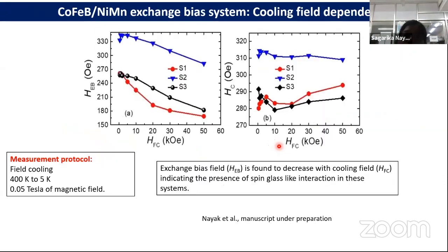Similar to our previous study, in this study also we performed a field cooling dependent study to study the role of the interface in these exchange bias properties. We found, similar to the previous study, that there is a decrease in exchange bias field with cooling field, whereas the coercive field is nearly constant, indicating that yes, there is a presence of spin glass frustration in this system.